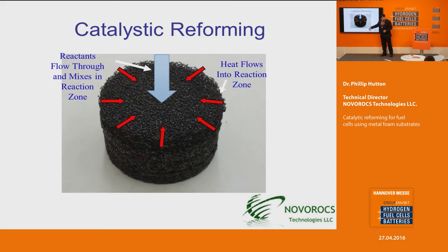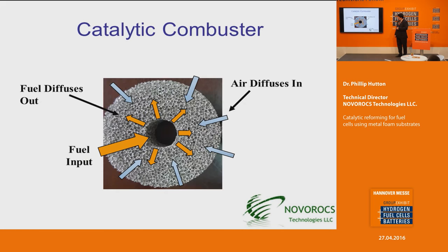Just to give you an idea of how a catalyst would work for reforming, what we're seeing here is basically several catalysts stacked on top of each other. We would put this in a reactor with the reactor vessel on the outside. Heat would flow from the outside in towards the middle of the reaction zone. The reactants would come through the actual foam and react, and because you have good heat flow, you have greater activity, greater reactivity between the reactants.